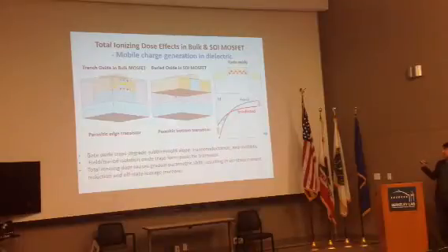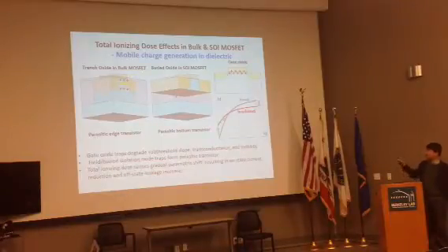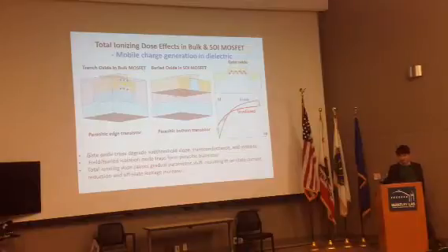So the overall result is seen like this. As time goes by, the off-state leakage goes up because of the localized high trap density in the sidewall, and the drive current is reduced because the mobility of the channel is degraded. This behavior gets worse and worse as time goes by. Once it shifts too much from the design tolerance, the system no longer works.